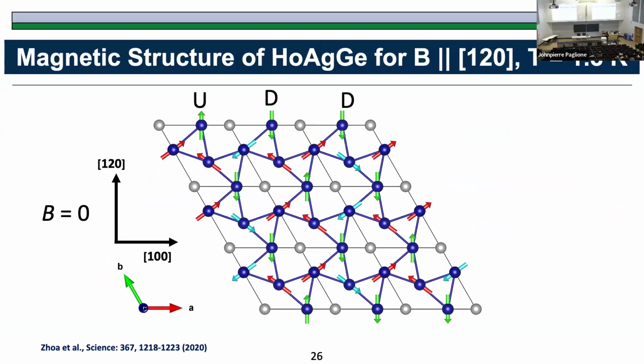Any spin that has some positive component along 1, 2, 0 is red. So you can resolve this in this component here, right? All these spins have a positive component in this direction. If a spin has a negative component along that direction, then that's blue. When you apply a magnetic field in this direction, first it wants to flip these that are parallel to the field, because the magnetic field talks to them easier, right? It flips this one spin and you get one step. You increase the magnetic field, it flips another spin, you get another step, right?